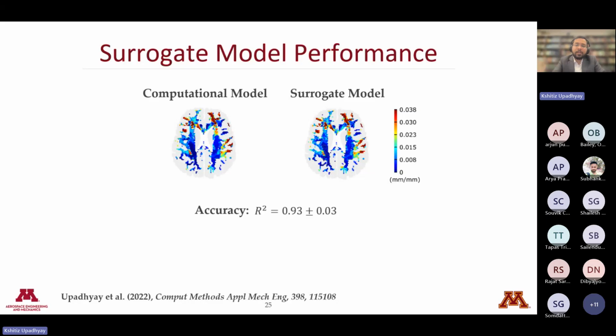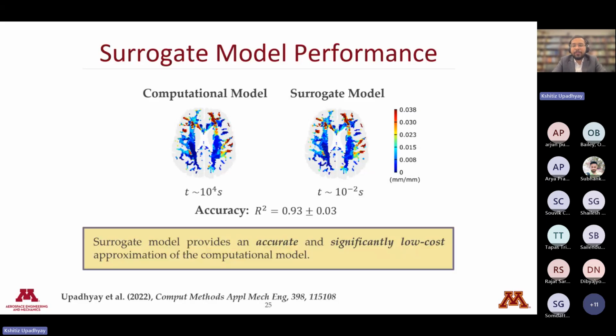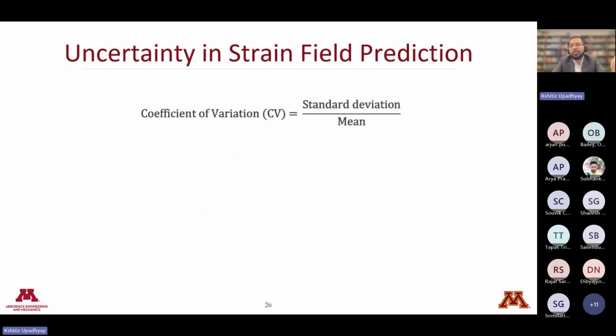Now, not only are these fields accurate, but we also found out that we get almost a million times cost reduction. The surrogate model used to give predictions in 10 milliseconds, which is a huge reduction from the hours that the computational model used to take, even on an HPC. And by surrogate model, I'm talking about running on my laptop. Okay, so the surrogate model provides an accurate and significantly low cost approximation of the computational model. And so using this surrogate model, we propagated uncertainty and calculated a coefficient of variation as an uncertainty metric.